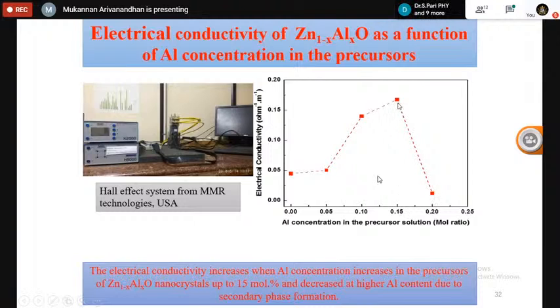So up to 15%, the aluminum has been systematically substituted at the zinc site, and due to the heterovalent nature of aluminum, the conductivity has been enhanced. Due to the formation of the poorly conductive alumina secondary phase, the electrical conductivity has decreased for the high content sample.